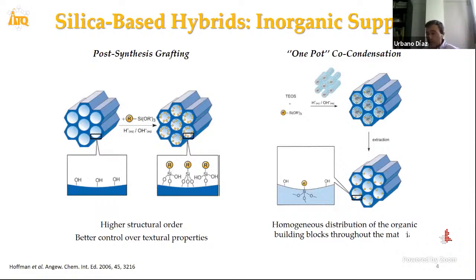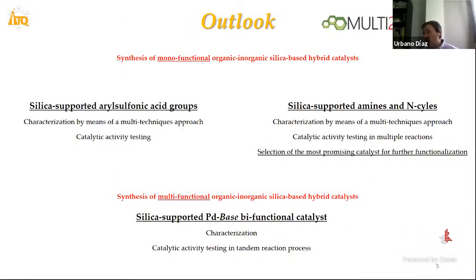In the framework of the project, we have obtained a great variety of hybrid materials with mesoporous character, directly through one-pot co-condensation, or through post-synthesis grafting and micellar routes. With this methodology we have obtained very large families of hybrid mesoporous materials, and even periodic mesoporous organosilicates, for example from the University of Southampton, obtained when only bridged silsesquioxanes or disilanes are used as organosilicon precursors. So a great variety of organic-inorganic mesoporous hybrid materials, with different functions incorporated in the walls of these solids, were synthesized in the framework of the project. I can show several examples in the next slides to illustrate this type of hybrid materials.